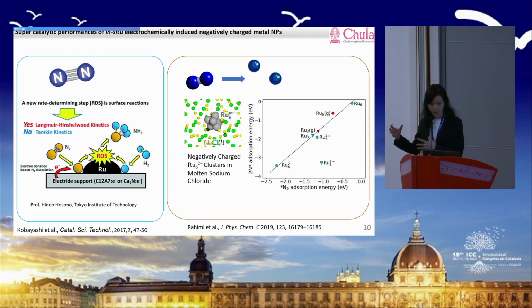And here they show the ruthenium on the electride support, although they didn't call it negatively charged ruthenium, but electron transfer from the electride support to ruthenium. It even changed the ammonia synthesis, in which, as is well known, nitrogen dissociation has been the rate-determining step. There's no longer a rate-determining step on this ruthenium catalyst, just a surface reaction between adsorbed nitrogen and hydrogens. There are also some other techniques that you can use to create negatively charged metal clusters.